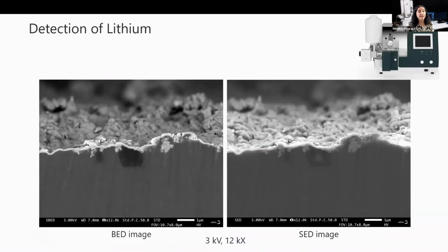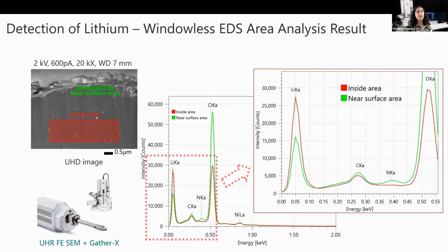Here's an example of lithium metal which has been cross-sectioned. And here are the spectra taken at a position near the surface and at the inner area of the cross-section. You can see the very clear lithium peak in both spectra, and that the near surface area shows more oxygen and less lithium.